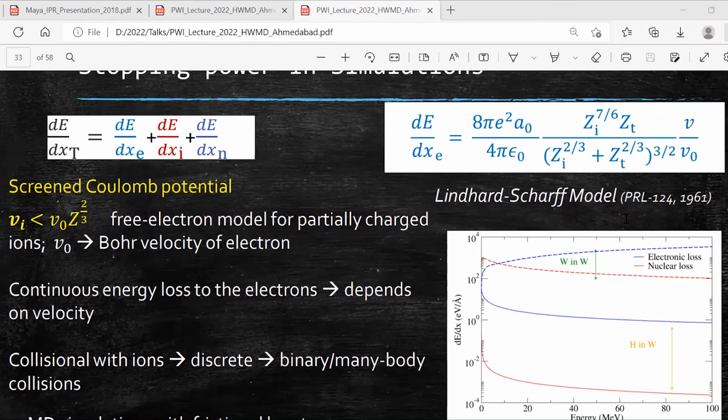So you say that this much energy is going to the electron system, which is not going to affect my defect formation. But it can affect, for example, a semiconductor: if you do the same thing, then this loss to electrons can actually create tracks. This is one of the reasons why solar cells sometimes fail, because ion bombardment in space can create tracks in the system. So there you have to use the full quantum calculation. It depends on the problem that you have.